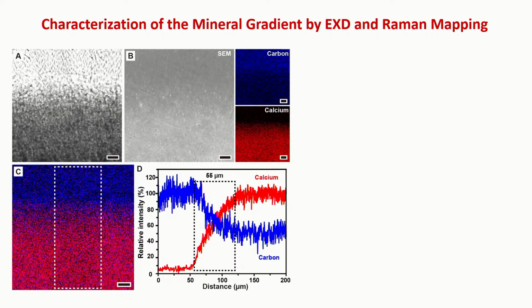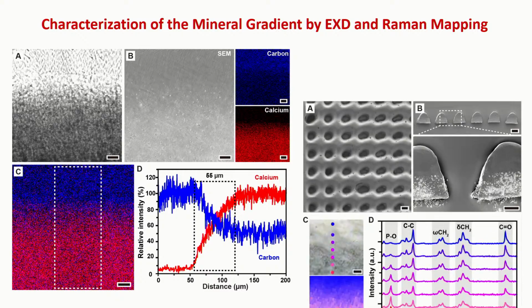And here, just to show you some characterization. This is a cross section we made. You can see the gradient from the EDX mapping. The calcium concentration will increase. And in particular, it's very nice. Now we can generate this kind of junction with relatively thin thickness that can really match the native transition site, typically about 50 micrometers. It's a very thin layer overall.